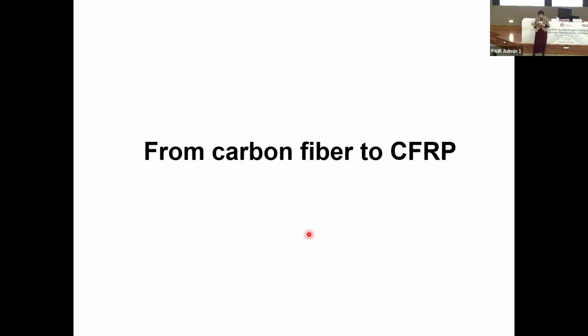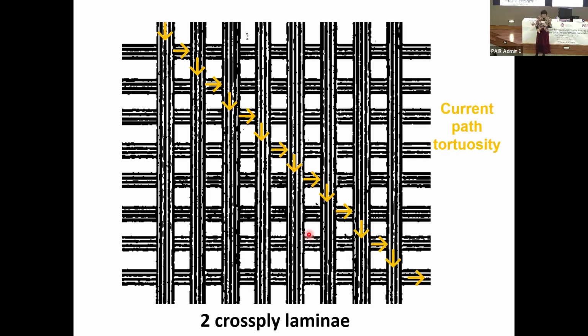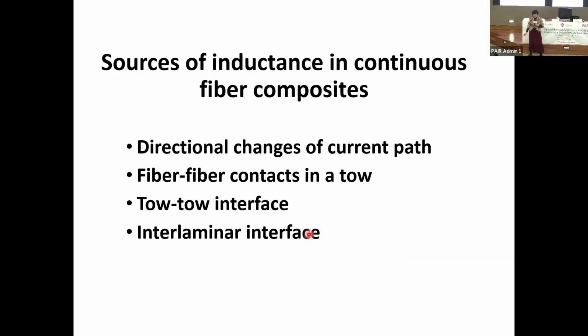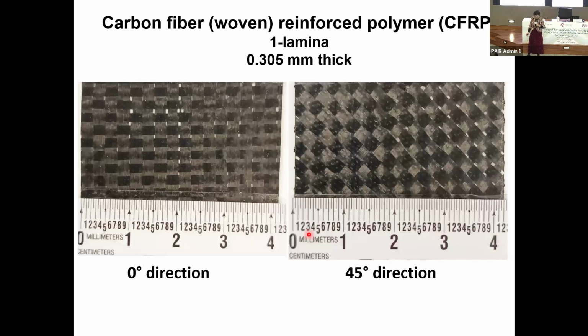Now, I want to move from carbon fiber to CFRP in terms of the inductance story. This is 2 cross-ply laminae, and the arrows indicate the current path tortuosity. And it's not coiling, but it's a bit like coiling. And so this tortuosity would contribute to the inductance. Sources of inductance in the fiber composites include not only the directional changes of the current path, but also the fiber-fiber contacts within the tow, also the tow-tow interface, and the interlaminar interface.